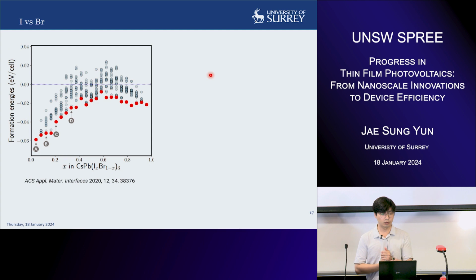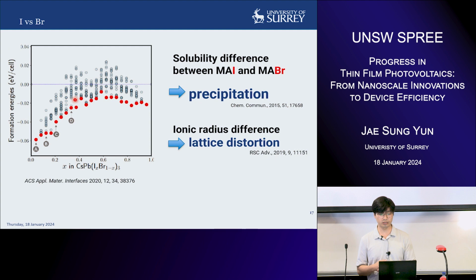So what happens when you mix iodine and bromide? So people report that the formation energy of these materials are different. So if you mix them, you will eventually have sort of quite inhomogeneous or uneven crystal structure formation. So there's a structural growth difference which can be due to the solubility difference between these two halides. So there are going to be some precipitation, and there is also difference between iodine and bromide.